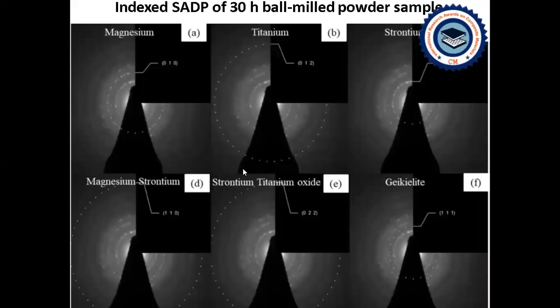And these are the indexed SADP patterns of the ball milled powder for 30-hour duration, and these are the HKL indices. After indexing each diffraction pattern, it is found that similar elements were present, and these results were confirmed with the XRD results, as the same elements are present in the ball milled powder sample.